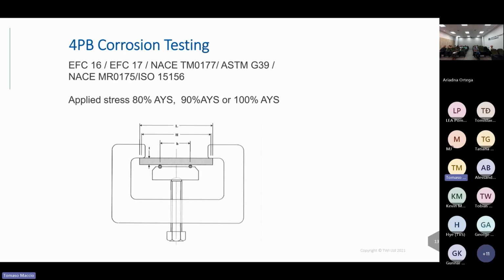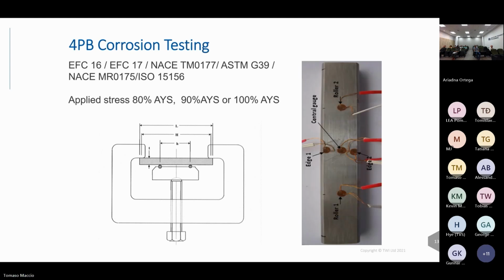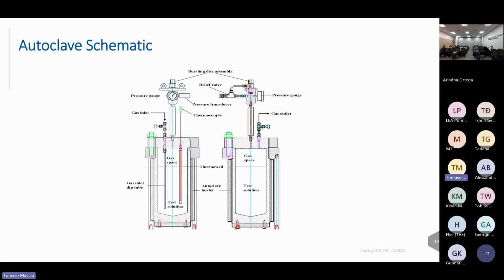So coming up in the next 2 months, there's some 4-point bend test corrosion testing to take place with different stresses applied, and that'll be completed in our laboratories in Cambridge, and then also with ÍSOR, our colleagues in Iceland. And then there'll be autoclave testing, so in a brine solution or a solution similar to that of the geothermal environment, testing samples coated and uncoated, and measuring the weights of the samples afterwards to see the losses caused by the corrosive solution.